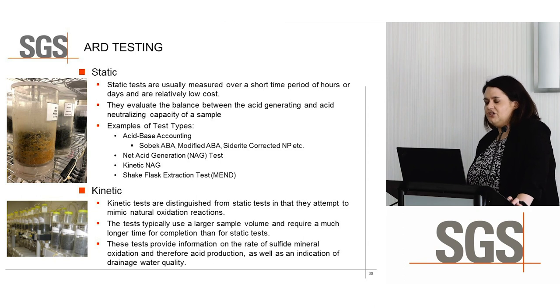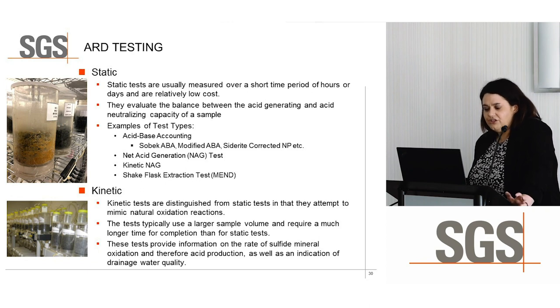period of time, generally 40 weeks, you're testing the oxidation of particular minerals, if you're looking at your sulfides, or the neutralizing potential of your carbonates. And basically these tests provide information on the rate of, as I mentioned, the sulfide mineral oxidation and therefore acid production, as well as an indication of the drainage water quality.